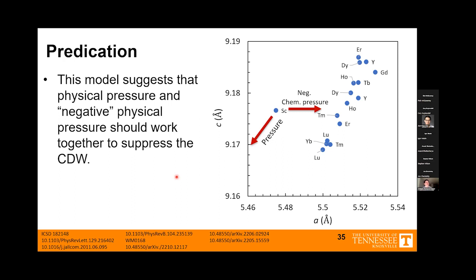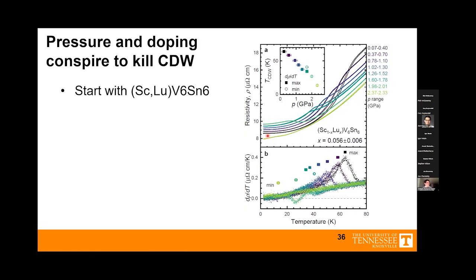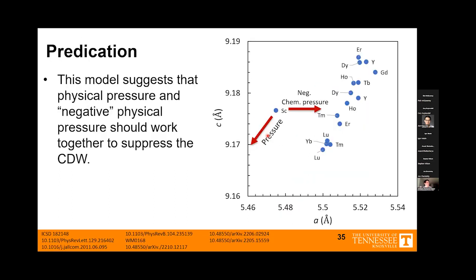We're using the bigger atom to fill up that volume, and we're using the pressure to squeeze the network around it. So what you can see here is our family of rare earths on our C versus A plot and our scandium. And the negative chemical pressure by doping either expands or fills up that channel without changing the C lattice parameter. And physical pressure compresses the lattice. So this makes a prediction.